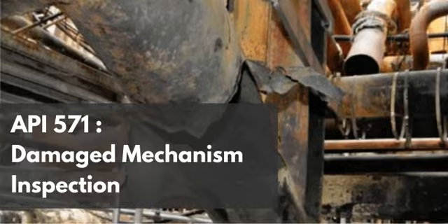The inspection records specifically note that because of this geometry, the shear wave UT inspection originally mischaracterized the corrosion as mechanical cracks. Wait, seriously? Mischaracterized as cracks. So the ultrasonic wave bounces off the sharp geometry of the corrosion groove, and the signal on the technician's screen looks fundamentally identical to a crack instead of presenting as volumetric metal loss.